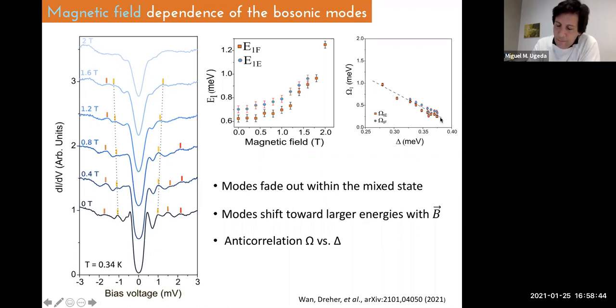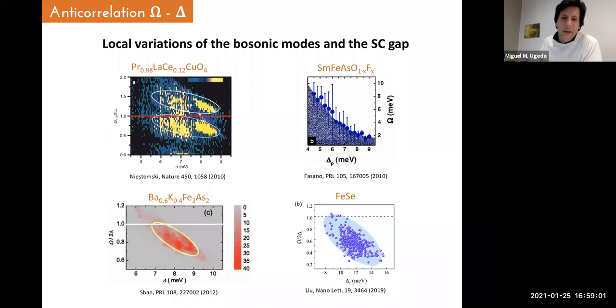So as the superconducting gap decreases, the omega, or the spin excitation energy, binding energy increases. So it follows an anticorrelation. This is something that has been observed before in other superconductors. So here I show you previous measurements of the fundamental mode against the superconducting gap for four different materials. These are cuprates, for example. In all of them, they show an inversion relationship similar to the one that we observe here.